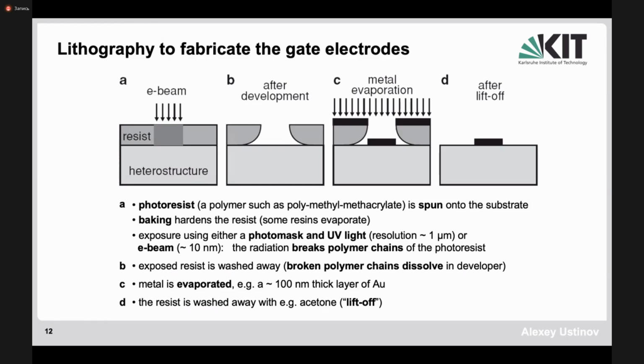Then you evaporate metal from the top, and then you put everything in acetone, and you remove this resist and the resist on the other side, together with the metallic layer on top, and what you are left with will be a very narrow metallic electrode. So this is really something standard for semiconductor technology when one works with these low-dimensional transport structures. So this is the way you could make very narrow electrodes of the size of, let's say, down to 20 nanometers or so.